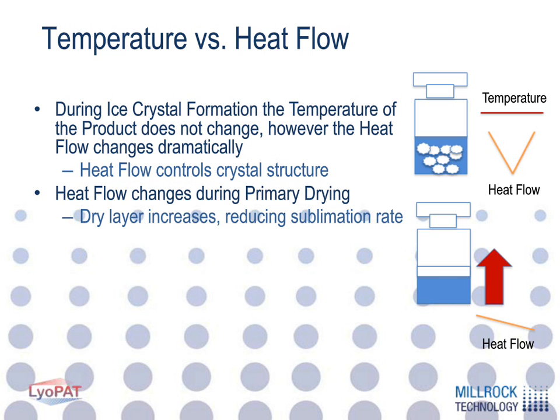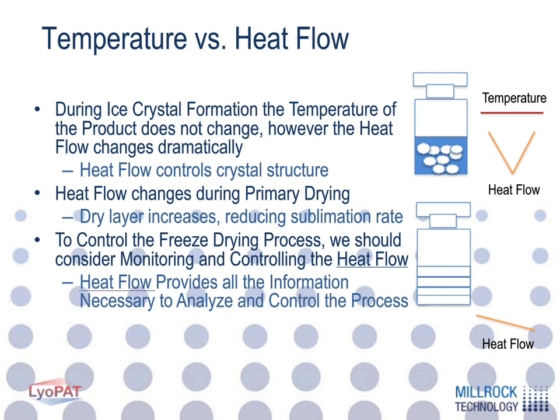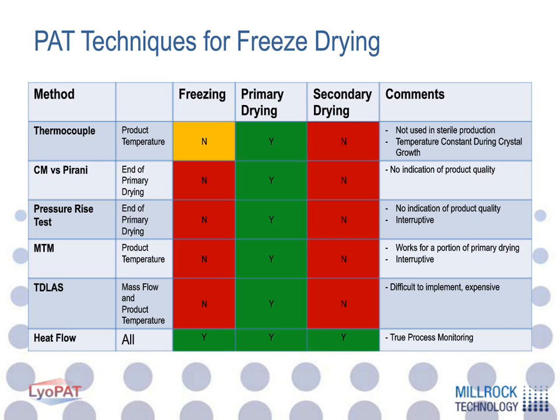Now, during primary drying, you have a slightly different effect where the dry layer increases and your sublimation rate changes. And depending on how the product was frozen, we can actually see the heat flow change over time. You'll see that in some cases the heat flow doesn't change much at all, or in some cases it changes pretty dramatically. If we look at some of the more common, what are referred to as PAT techniques, you'll notice that most of those really only work in the primary drying process. Thermocouples, capacitance manometer versus Pirani for endpoint determination, pressure rise testing for determining product temperature during the primary drying phase, MTM, TDLAS. The only one of the techniques that actually works for the entire process would be a heat flow measurement.